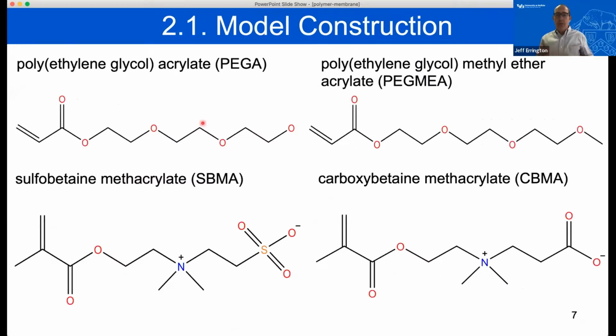As I mentioned before, one of the keys was that we wanted to compare the base membrane to different polymer tethered surfaces. And we were interested in understanding the differences between the performance of different zwitterionic types of polymer grafts, as well as non-zwitterionic polymer grafts. And so, again, we turned to Professor Lin's group and asked for some suggestions in terms of what to use. And they had indicated that a couple of the ones that they work with from a non-ionic perspective are polyethylene glycol acrylate and polyethylene glycol methyl ether acrylate. So we'll call those PEG-A and PEG-MEA.